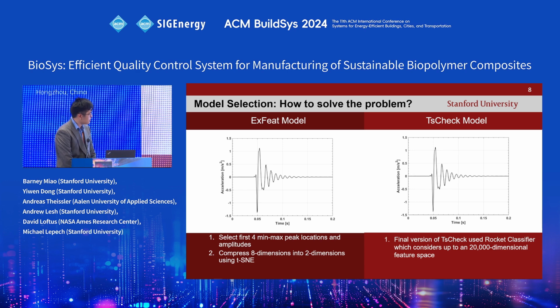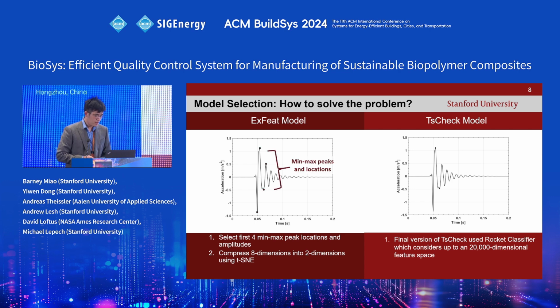For our model selection, for our XFeat model, which is our simple model or quick and dirty approach, we select the first minimum and maximum peak locations and amplitudes. If you select them, you eventually have 8 features you're considering, which can further be compressed into 2 dimensions using t-SNE. So this is a very quick approach that takes only a few seconds to train, typically less than 10 seconds.